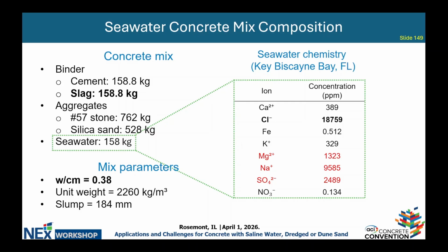Here, I would like to highlight two main things about the mix design of the concrete. The first is that we used a 50% slag replacement level. The other is a relatively low water-to-binder ratio of 0.38. Most importantly, we used seawater taken from Key Biscayne Bay, located in Florida. This table shows the chemical composition of this seawater with different ions, including chloride, magnesium, sodium, sulfates, etc. So it's not just a simple replacement. It's a replacement that will introduce aggressive ions into the concrete that will interfere with the durability of this system.